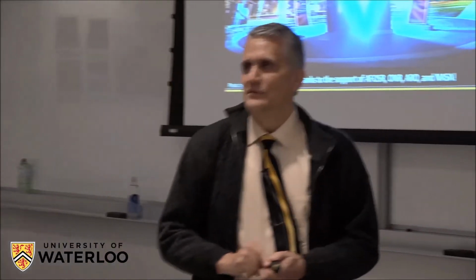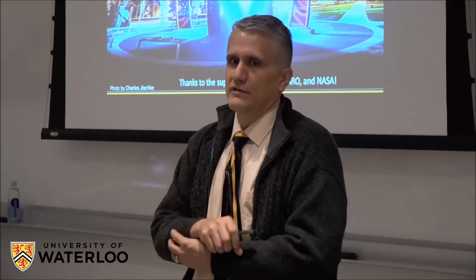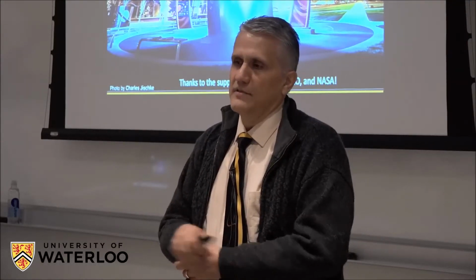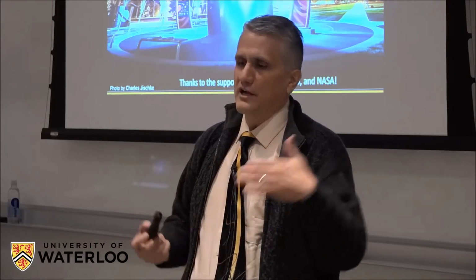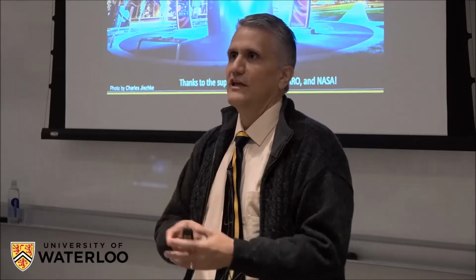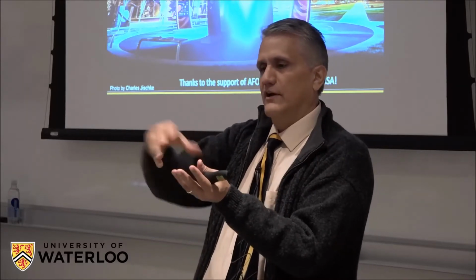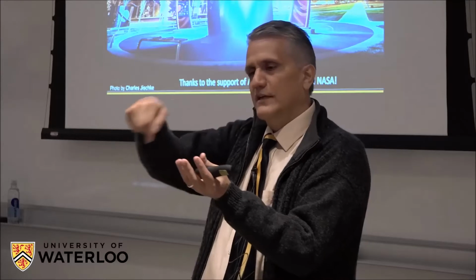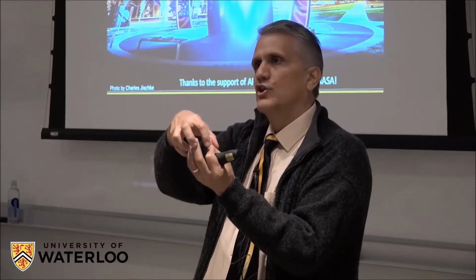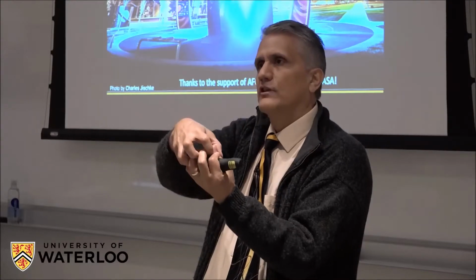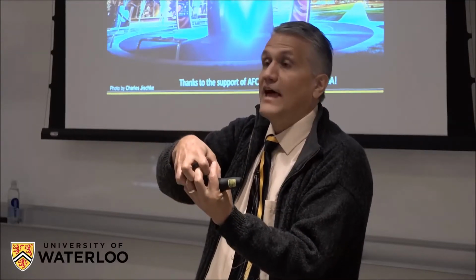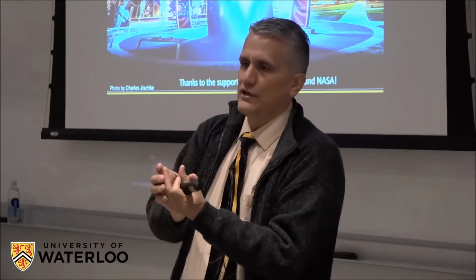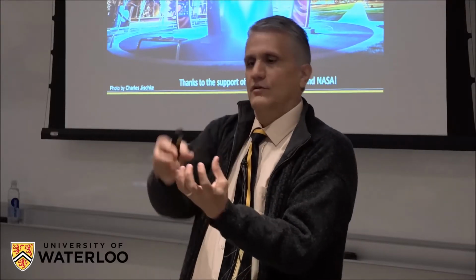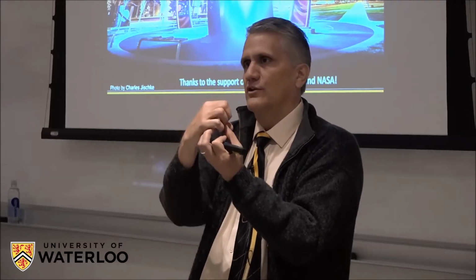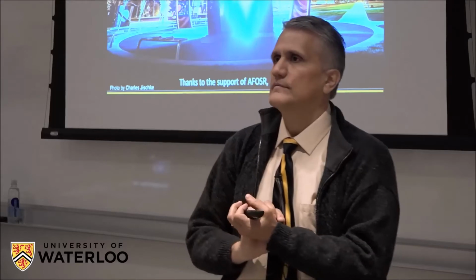For your 3D printing, what's the layer strength like? Because I know that's a major issue. Oh yeah, absolutely. Conventional ones. Yeah, we're looking at that really vigorously now. There's a lot of times UV cured binders, and the problem with that is when you cure a layer. If you print things that aren't cured, then you apply the curing, either heat or whatever, then the layer to layer will intertwine, and that layer to layer adhesion may be pretty good. But if you have a UV cured binder, then you kind of close off those molecules for binding to the next layer, and that could be a huge problem.